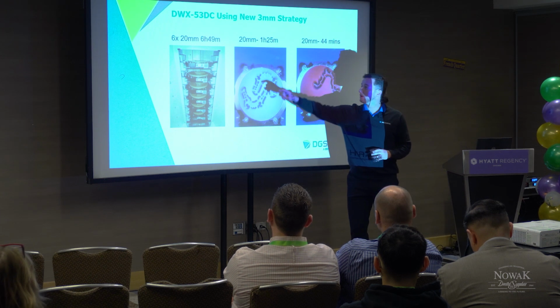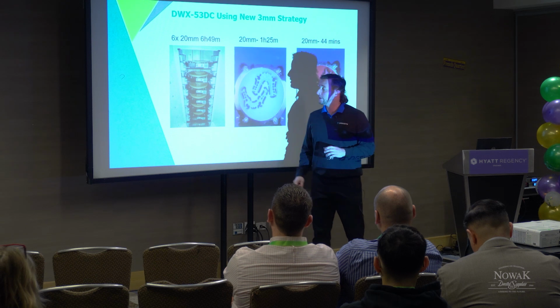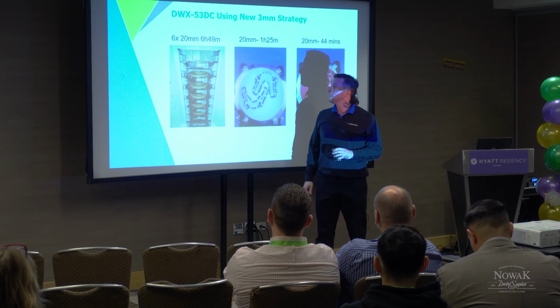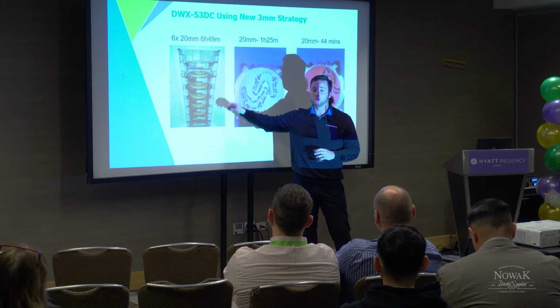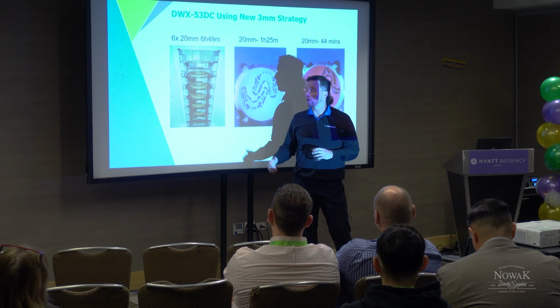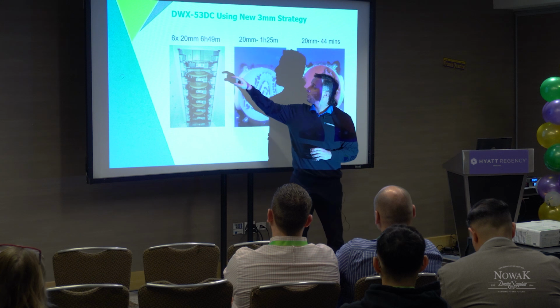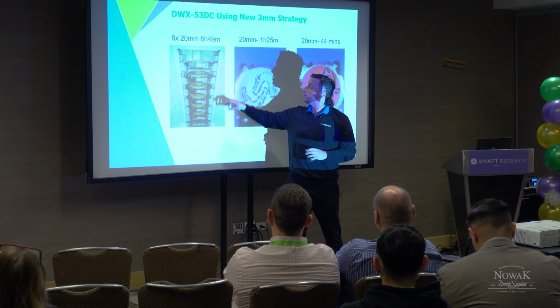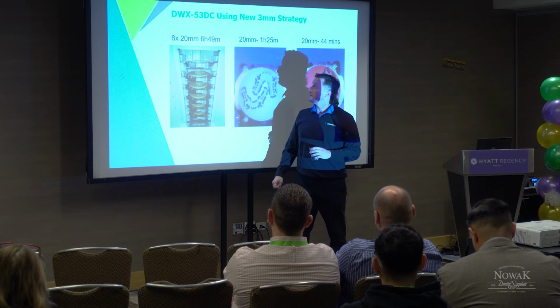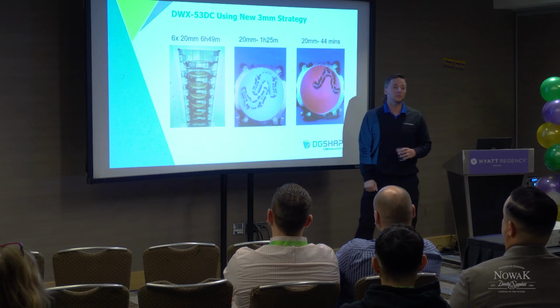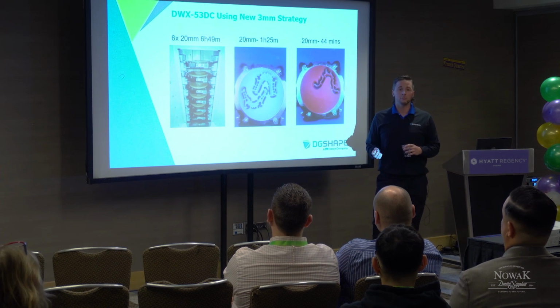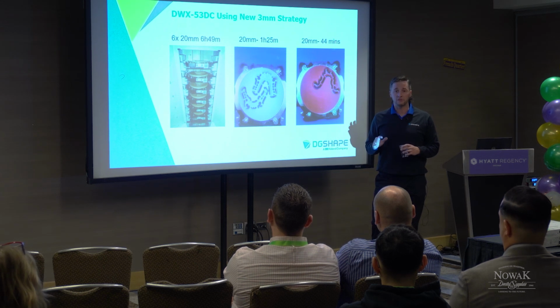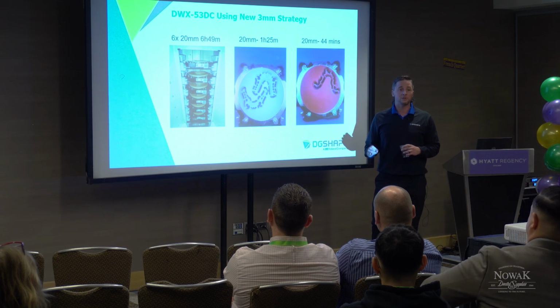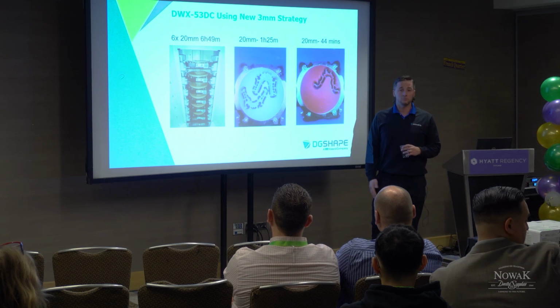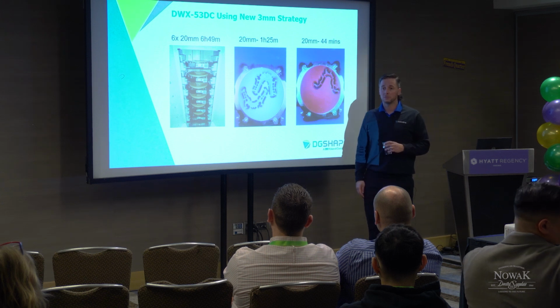The first job here is denture pucks milled out of PMMA. We loaded this at night with the new, I call it boosted strategy, the more aggressive strategy. And we were able to load it with six pucks. All of these jobs were completed in 6 hours and 49 minutes, which means we're milling denture bases in just over 1 hour at this point. In many cases for lower dentures, we are hitting that 50 to 55 minute time frame, which is significantly faster than where we were with the 52 just 6 months ago.